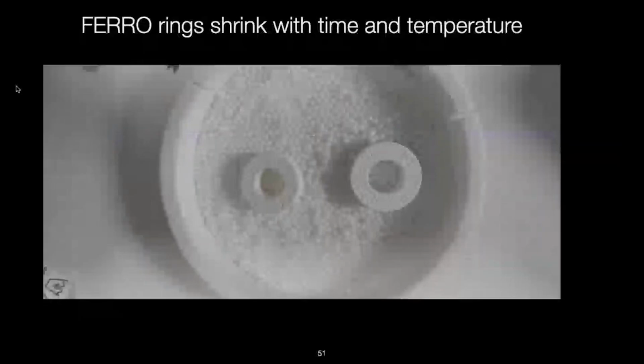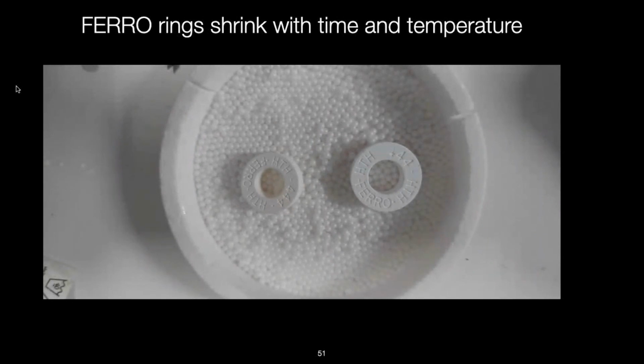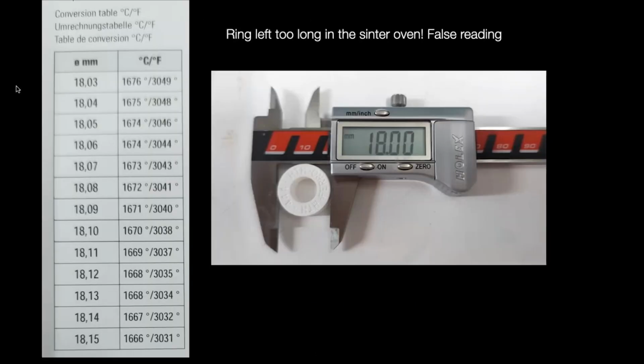So the mistake that I made was saying, well, I want to put it in there while my crowns are in there, which sounds novel. The problem is the longer that the ring stays in there, the more it shrinks. So I put a shrunk ring in there and I put a new one next to it, and you can see how small that is. And what happened was I put like a 4-hour hold and it kept shrinking down to nothing. So when I tested it and I looked at the chart, you can see at 18 millimeters, it starts off at 20. The outside diameter is 20.